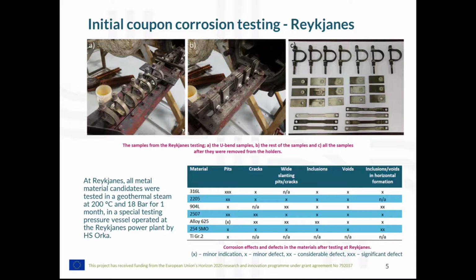some caused by the exposure itself, but what we learned during the project, well, we knew this of course, is that the defects marked there are also due to manufacturing in some cases, and in some cases manufacturing defects can accelerate corrosion or be a site for pitting or other corrosion which can degrade material.